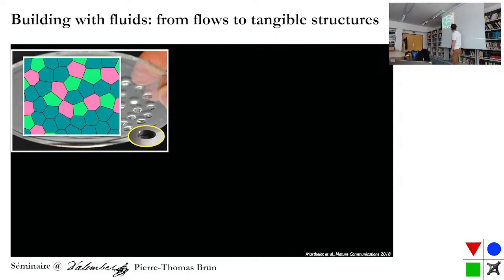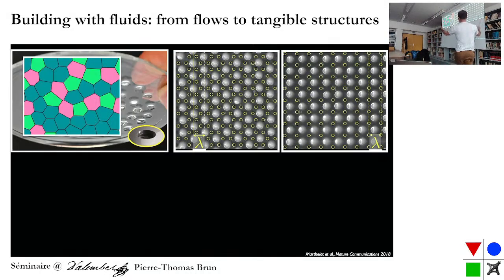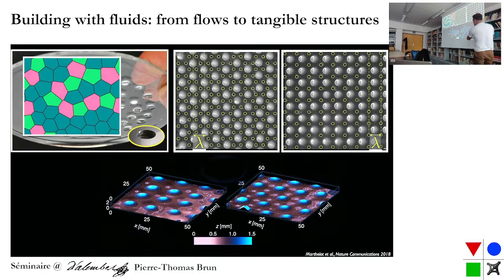So the distance between droplets is 2 pi square root 2 times the capillary length, so about 10 times the capillary length. And if you respect that and you run the experiment again, then you get a very nice network of droplets, right? So you can have a hexagonal, triangular lattice if you want, or square lattice. And in both cases, these drops now have the same size, right? So you can tame this instability by providing defects in your initial condition, which will be amplified by the instability. So it's a bit like the first story I mentioned.